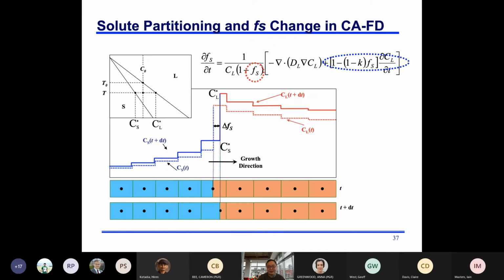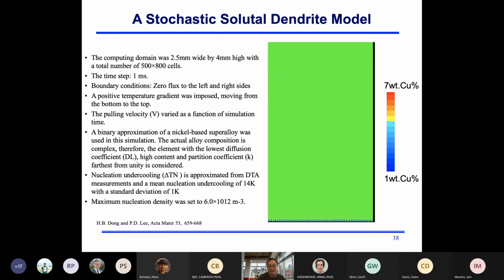We call this solidification theory. So if you look in a bit more detail, in the center, these will be growing cells. Those growing cells are controlled by this equation. Essentially, this is diffusion in the liquid, and this is the solute partitioning at the solidification front. So you apply this to the whole computation domain, and if you have a large domain, it takes a longer time, right?